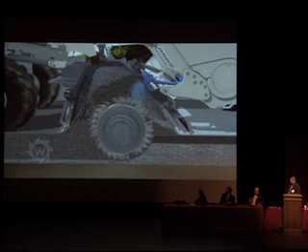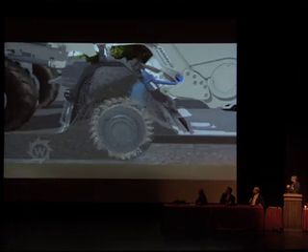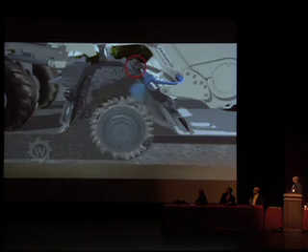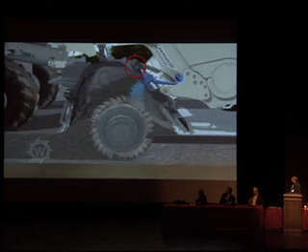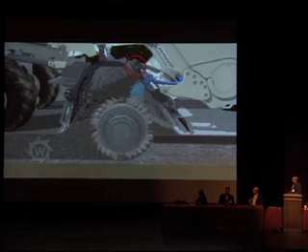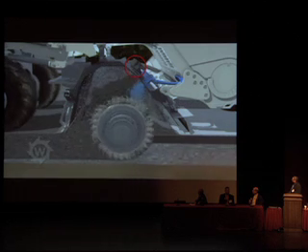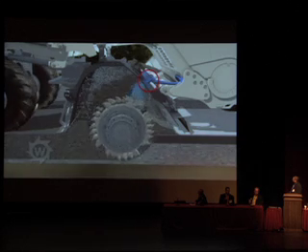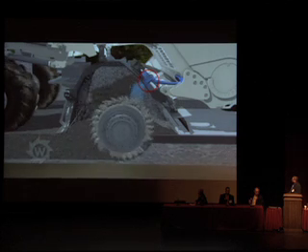The powerful milling and mixing rotor granulates the damaged pavement layers. The pre-spread cement is mixed in at the same time. A special injection bar with expansion chambers produces the foamed bitumen and sprays it in. Water added to the process causes the bitumen to foam abruptly, expanding it to many times its original volume and distributing it evenly in the mineral aggregate mix. At the same time, the amount of water required for the mixing process is added via a second injection bar.